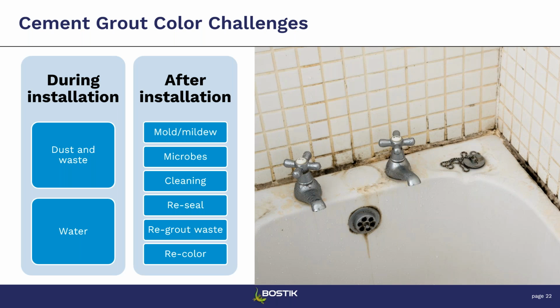With cement grout in particular, there are color challenges. So during installation, you can have dust and water challenges, which means some dust in the air can affect the way the grout dries and the color of it, as well as water. Accidentally getting water in can also affect the color of the cement as it dries. After installation, you do have that risk of mold and mildew. Any cleaning, so any acidic cleaners can affect the color. If you put it on too hard or if you scrub too hard with an acidic cleaner, you can actually dull the color or remove some of the coloring.